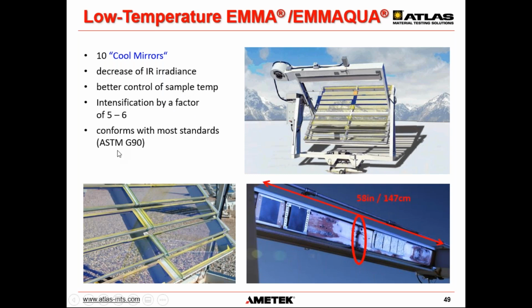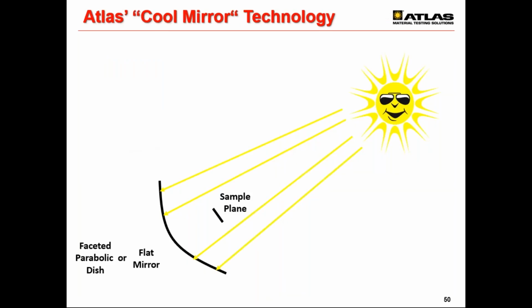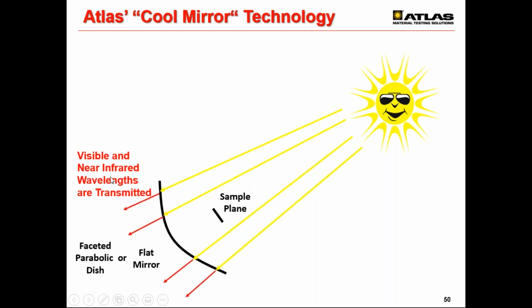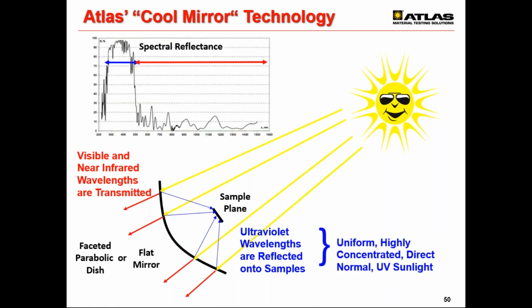And the way that this ASTM G90 standard is written now, these still comply with the wording in that standard. To kind of show the way these mirrors work, here, for example, pretend that we have our mirrors here on this parabolic tray that we see here. Okay, all of that light coming from the sun hits our mirror right here. All of the near infrared and some of the longer wavelength visible actually transmits through the mirror, so that only the UV and some of the shorter wavelength visible are reflected onto our sample plane that we see right here.